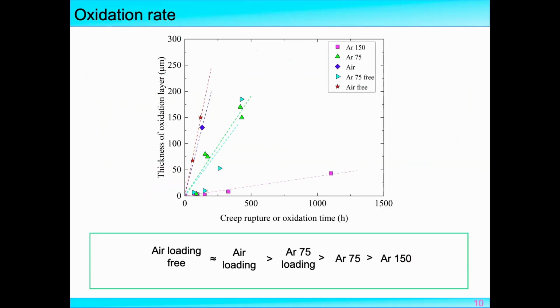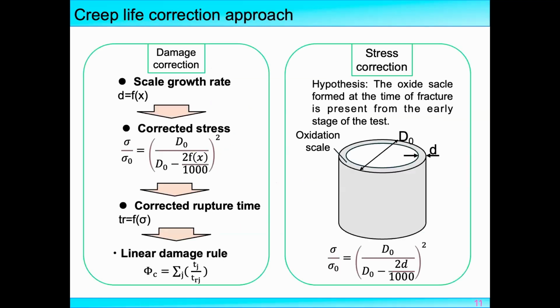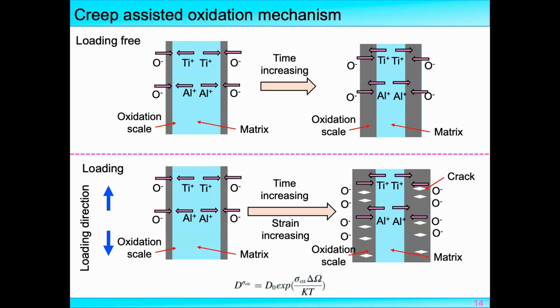From this figure, we can see that the oxidation behavior under creep loading is much higher. The oxidation growth rate is much higher than the loading-free condition. So here we give some explanation. For the loading-free condition, at the early stage, the oxidation layer grows by oxygen ion diffusion inward and titanium and aluminum ion diffusion outward, and the scale formed. With the increase of oxidation time, the oxidation scale grows linearly.